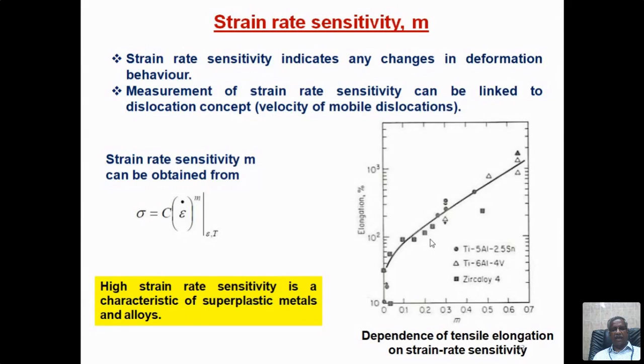The effect of temperature on flow property is well known. As temperature increases, definitely the strength will drop. Don't expect strength to increase. The metal or alloy becomes softened. The strengths, yield strength, tensile strength, fracture strength, all the strengths will decrease. The room temperature strength is always higher; at high temperature strength will always be lower. What are the materials? Even superalloys like nickel based alloys are good materials for high temperature application, but still if you measure the strength at room temperature and measure it at 600 or 800 degrees centigrade, it will always be lower than that.